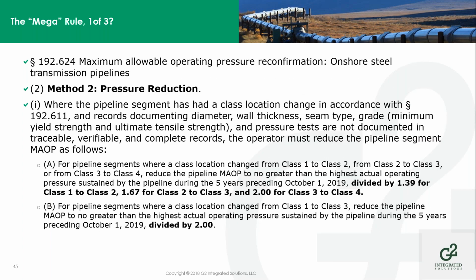Method 2 also talks about where the segment had a class location change. The pipeline where the class location changed from 1 to 2 or 2 to 3, you have to divide by 1.39 for class 1, 1.67 for class 2, and 2.0 for class 3 and 4. So you're going to take a big reduction if you do the pressure reduction method when you don't have the material information that you need.